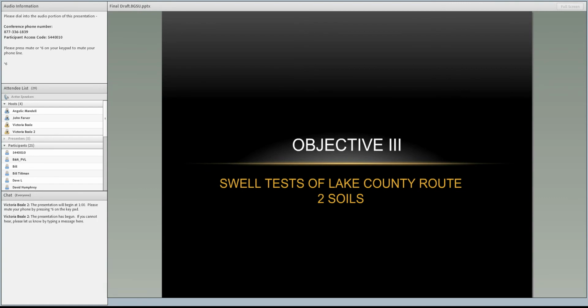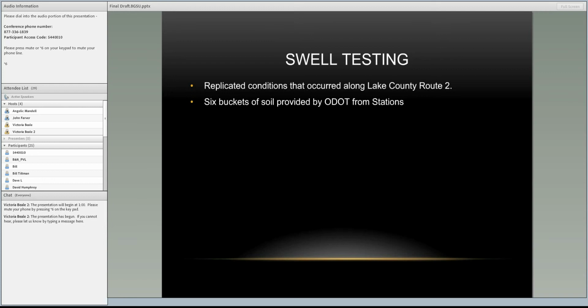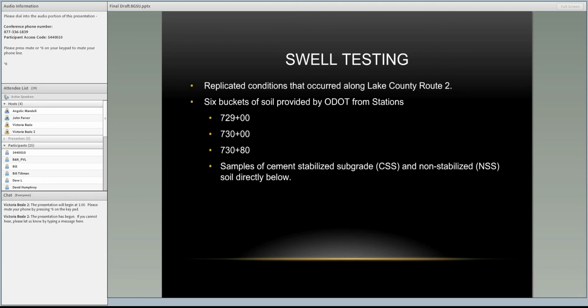So, with objective 3, what we wanted to look at is we wanted to perform swell tests with the non-stabilized soil to replicate conditions that we were seeing along Lake County Route 2. And as I've said before, we obtained 6 buckets of soil from ODOT. The stationings are 729, 730, and 730 plus 80. Each station had 2 buckets. One consisted of cement-stabilized soil and the other one of non-stabilized soil. And these areas were chosen because they were areas with significant heave and where full-depth pavement repair had to be done.